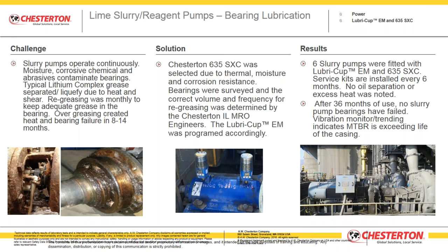In this case, after 36 months of flawless service, no slurry pump bearings have failed. Vibration and trending indicate that the MTBR of these bearings will exceed the life of the casings. So we've now been able to have the rotary unit, the drive end, exceed the life of the fluid end, such that when the casings are replaced, the bearing and the rotary components are still in good condition.